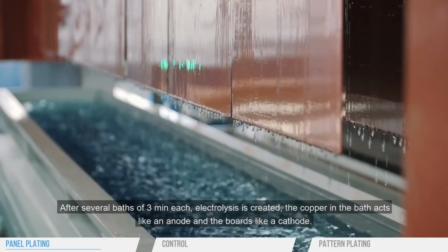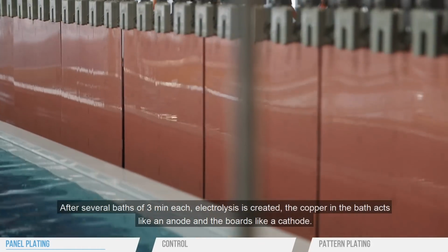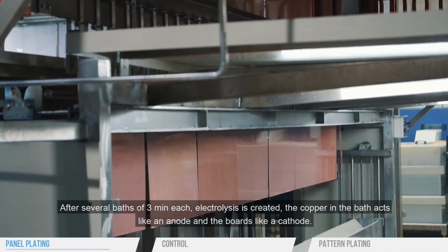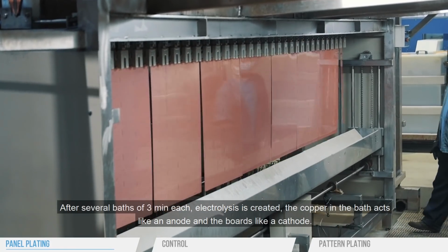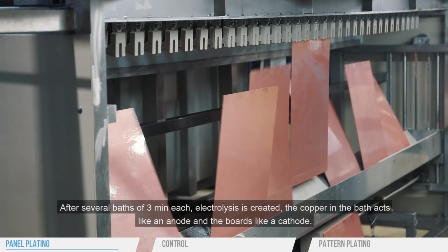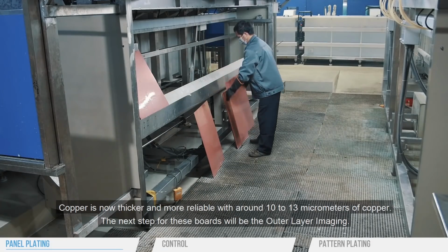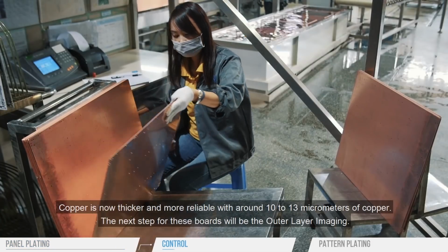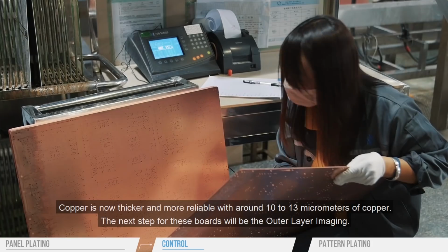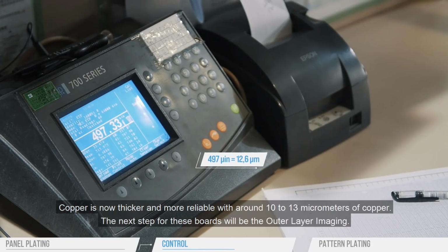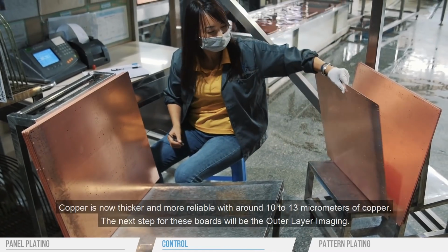After several baths of 3 minutes each, electrolysis is created. The copper in the bath acts like an anode, and the boards like a cathode. Copper is now thicker and more reliable with around 10 to 13 micrometers of copper. The next step for these boards will be the outer layer imaging.